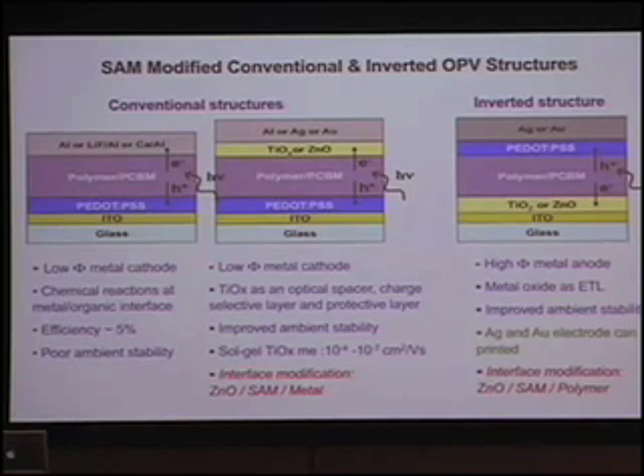So in order to really improve some of the optical properties, people utilize buffer layers to maximize the optical field. And also to provide some buffer layer on top, people utilize titanium oxide or zinc oxide to coat on top of this blend. People have had a certain degree of success. However, with titanium oxide, the electron mobility is around 10 to the minus 4 to 10 to the minus 3.